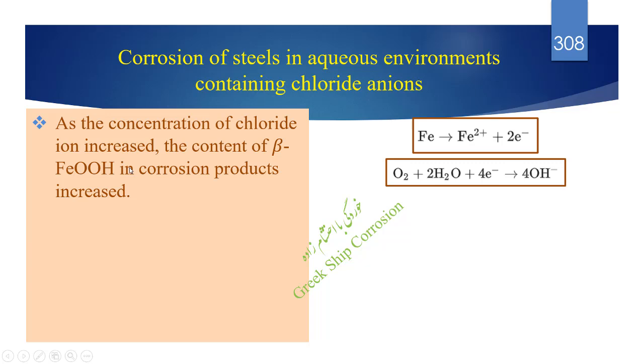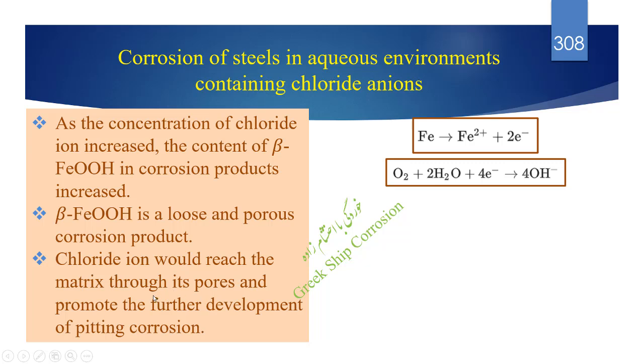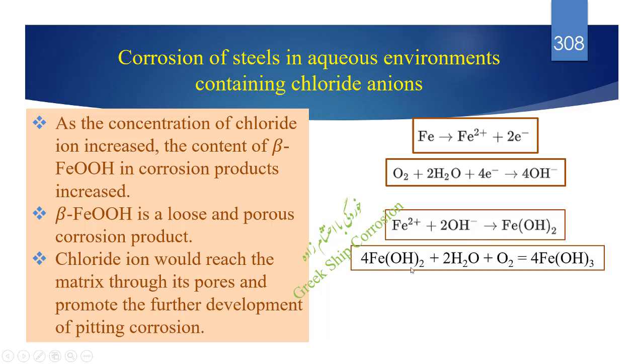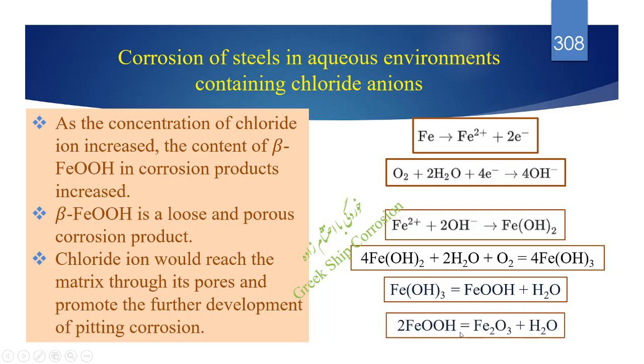As the concentration of chloride ion increased, the content of beta FeOOH in corrosion products increased. Beta FeOOH is a loose and porous corrosion product. Chloride ion would reach the matrix through its pores and promote the further development of pitting corrosion. Fe2+ + 2OH- yields Fe(OH)2. 4Fe(OH)2 + 2H2O + O2 equals 4Fe(OH)3. Fe(OH)3 equals FeOOH + H2O. 2FeOOH equals Fe2O3 + H2O.